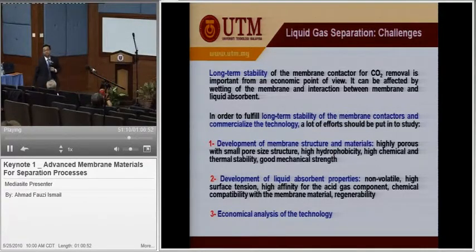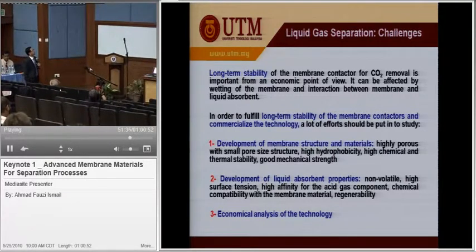But there are some challenges, not many. Long-term stability of the membrane contactor upon contacting with CO2 is very important. It can be affected by wetting of the membrane and interaction between the membrane and the liquid absorbent. So in order to fulfill long-term stability and commercialize the technology, there are about three things to be done. Number one, develop membrane structure and material. Second, find liquid absorbent properties. Somehow we use water, it's okay because I already patented it. Instead of any other chemicals, we just use water. Third, economic analysis of the technology.